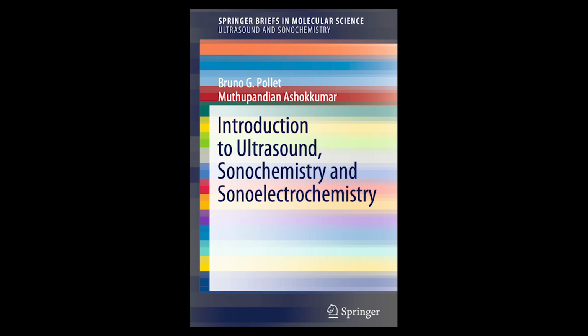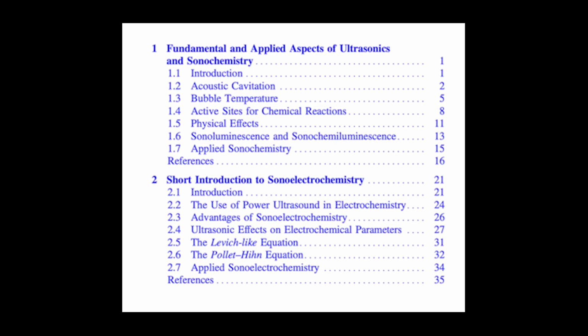Why is distinguishing this layer important? Because it's the crucial transition zone. This is where the superhot gas core meets the bulk liquid. It's where high-energy radicals generated in the core first encounter solutes from the solution. A lot of important chemistry, especially for making materials, seems to happen right here in this interfacial shell.